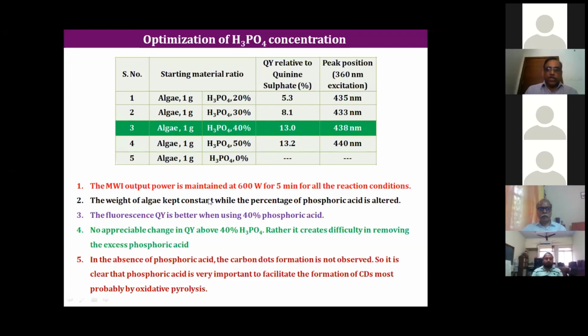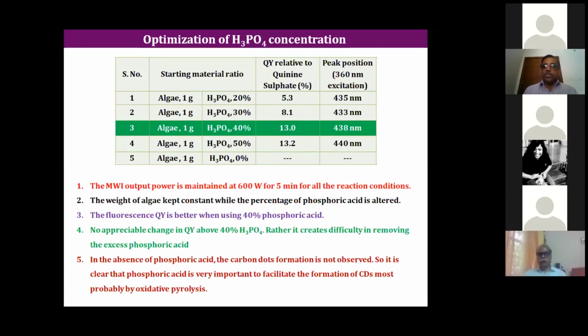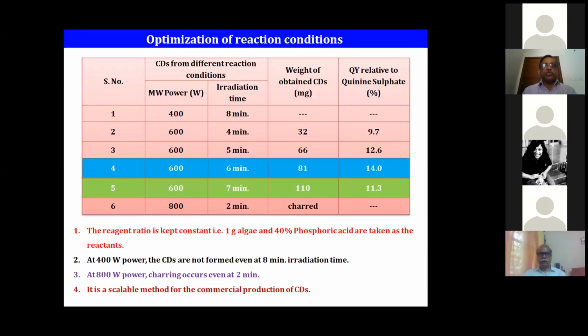Now this is how one can standardize the procedure of synthesis of carbon dots, varying the parameters and standardizing them when you have multiple parameter variations. Now, reaction condition - we also tune the microwave power and time of microwave irradiation. We found that 600 watt was optimal, and the time was around 6 to 7 minutes. We could get a good quantity of carbon dots also. So this is an important aspect.